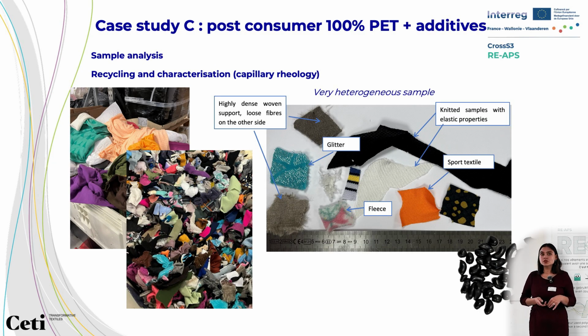This is a post-consumer sample, and here you can see how very heterogeneous it was. There is some glitter, there are some highly densely woven supports on the other side. We have some sport type textiles, some fleeces, and some knitted samples that have stretch properties. We can therefore, just from visual analysis, see not only polyester, an interesting mixture of possible contaminants in our process. We did manage to put it through the machine, and it did not stop our machine, so that's quite positive.